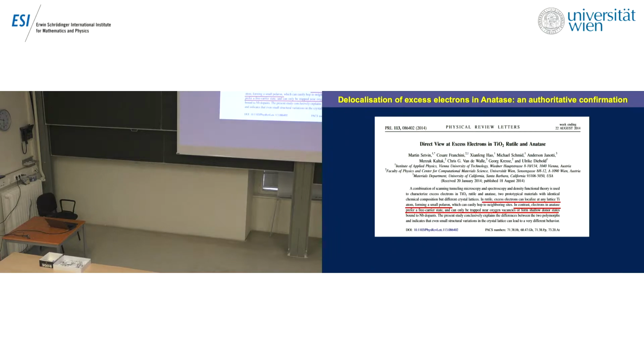Okay, so we imagine that this symmetry is due to the delocalization in some domain with an axial symmetry. To our satisfaction, a paper appeared in the literature practically at the same time by Ulrike, Cesare Franchini, Chris Van de Walle, Georg Kresse, so it's a paper with many important persons, okay, where by completely different approaches, scanning tunneling microscopy, they conclude that in rutile, an excess electron can localize at any lattice titanium atom forming a small polaron. In contrast, electrons in anatase prefer a free carrier state. So we are telling and sending the same message.